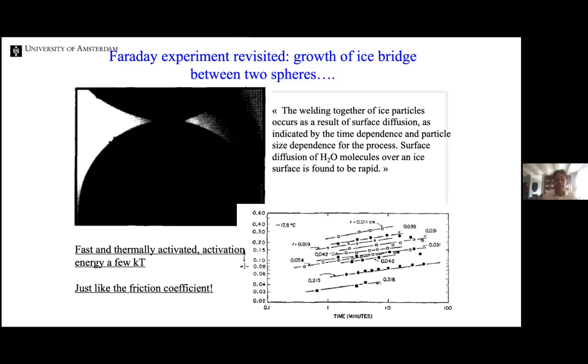And so Kingery concluded that this 1/7 law was characteristic of surface diffusion in this particular geometry. And so he said that the welding together of the ice particles is due to surface diffusion, which gives the 1/7 law, and which is very rapid. So here you see the radius growing over a period from 1 to 10 minutes. So this is a fast and thermally activated process with an activation energy of just a few kT, and that's actually exactly what we found for the friction coefficient.